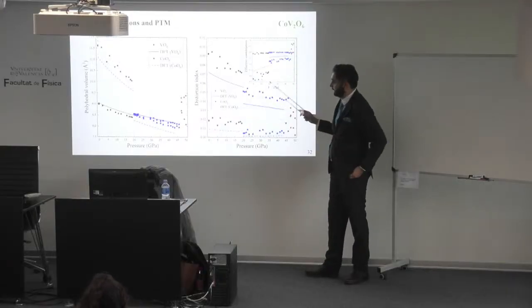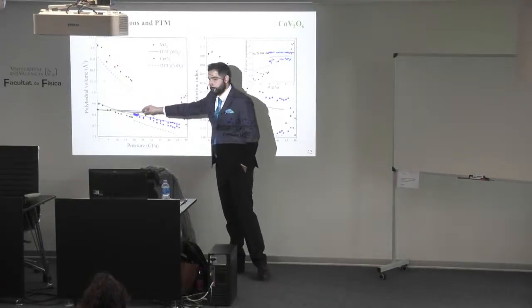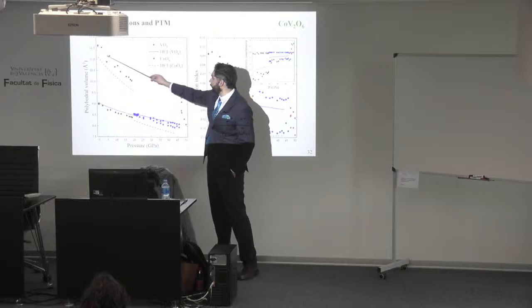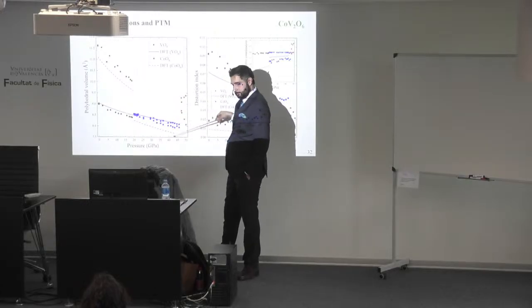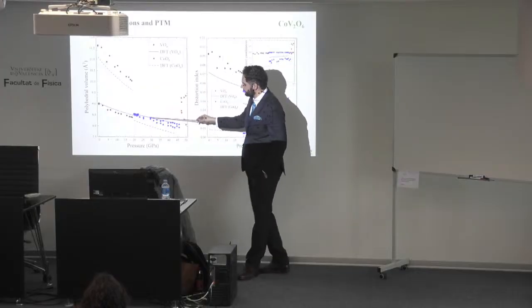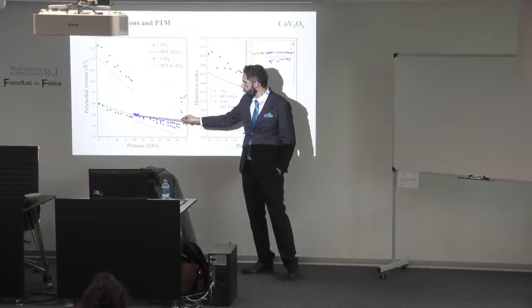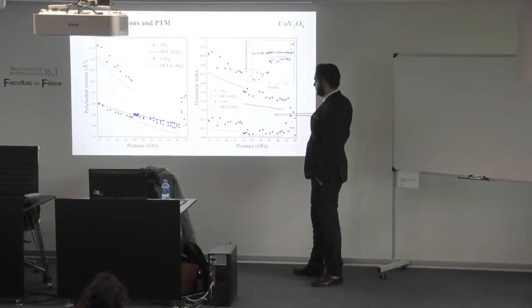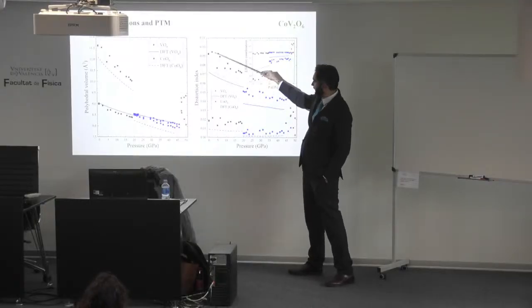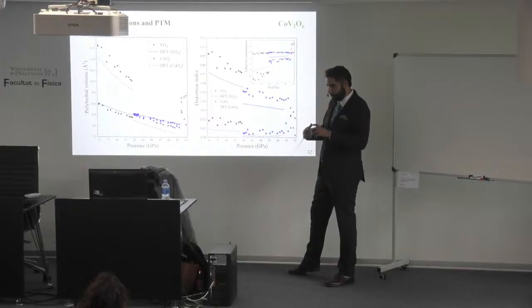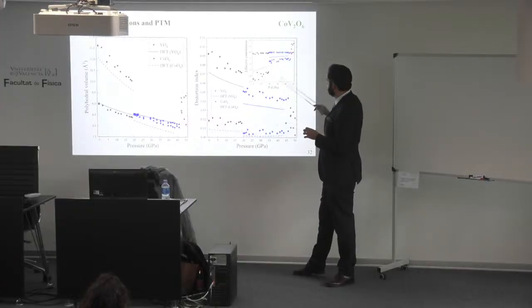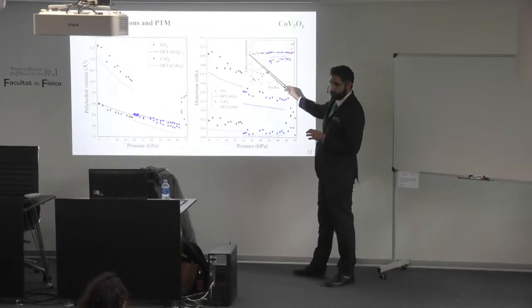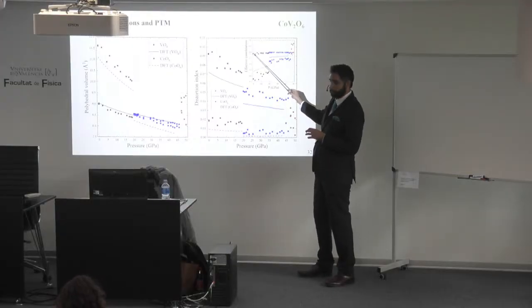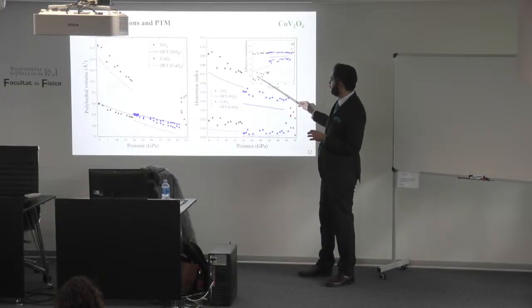So this is seen with the volume of each polyhedron. The cobalt one shrinks, and the vanadium one stays the same in volume, even goes a bit higher, but symmetrizes. The distortion index tells us that this octahedron is symmetrizing. And also you expect a 6 coordination in an octahedron. This is always true for the cobalt, but with the vanadium it gets closer with the pressure.